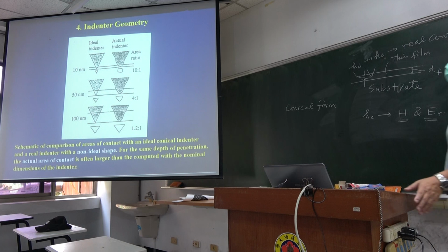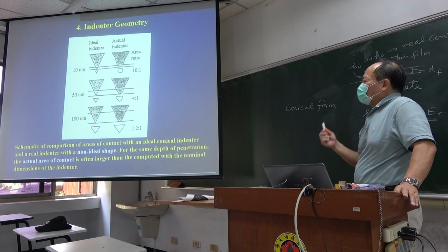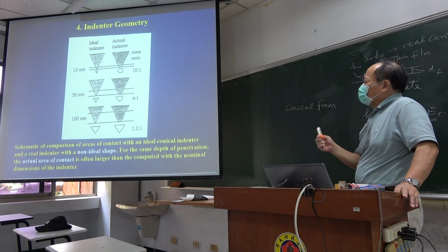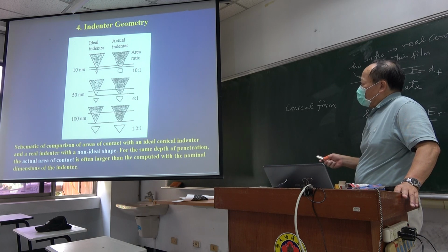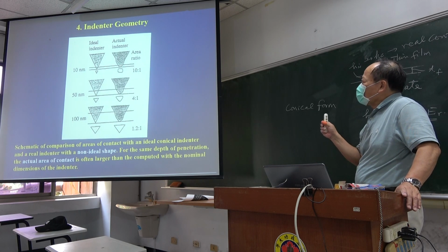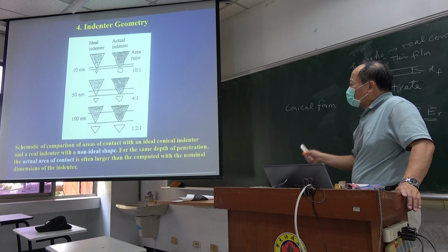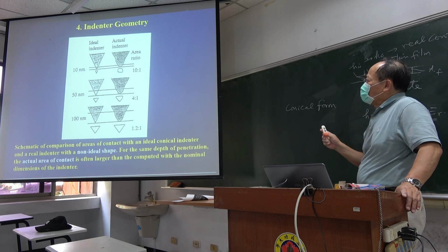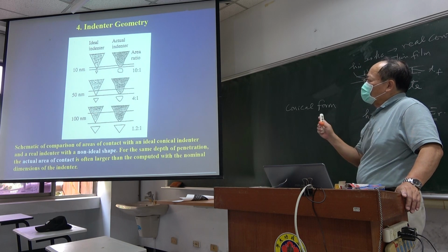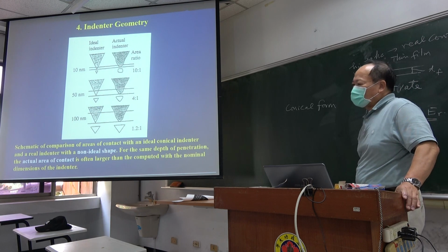So if your indentation depth is at a small value, the contact area created by the actual indenter is much larger than in the ideal indenter case.